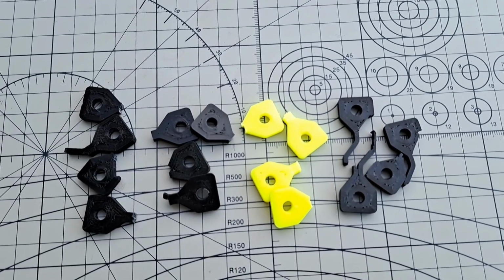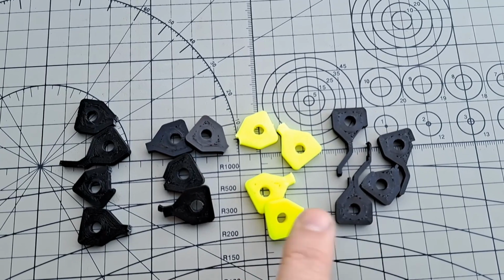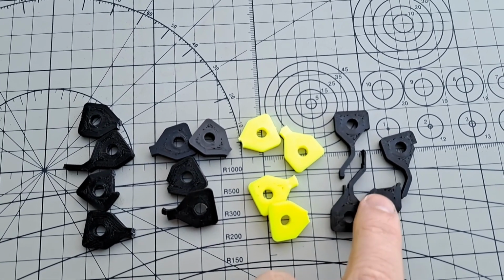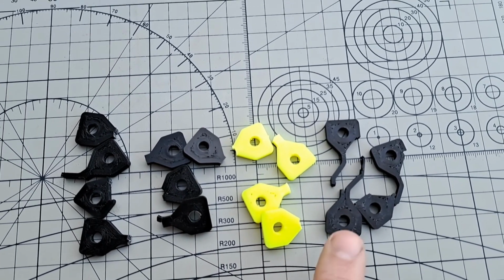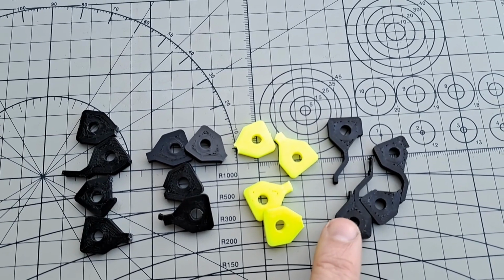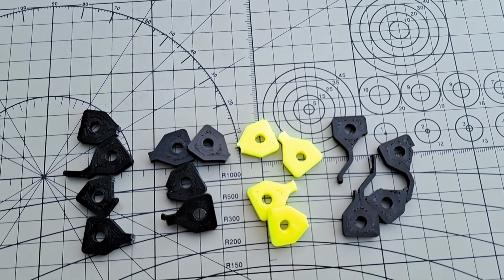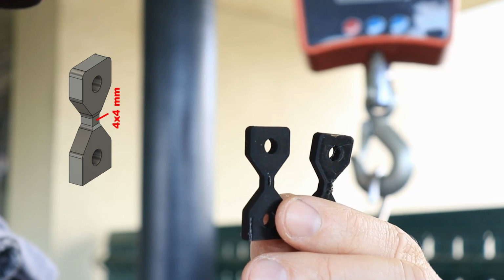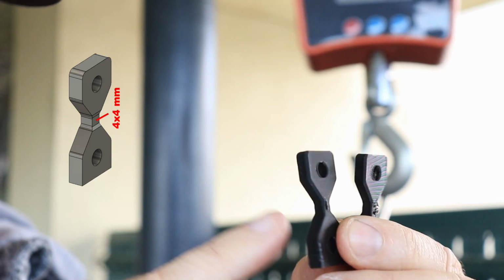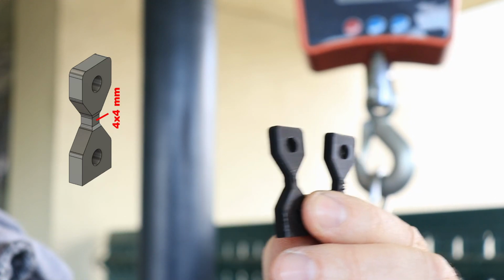And this is how they broke, and when I see a break like this, so not on the small cross-section area, this is a typical sign of weaker layer adhesion, but this was also weak in this tensile test too, so not too promising for the carbon version. And now the layer adhesion test with these vertically printed test objects. Smallest cross-section area is 4 by 4 millimeters.